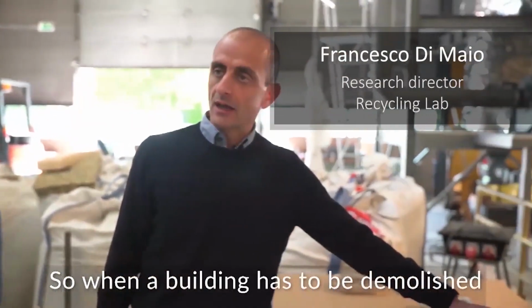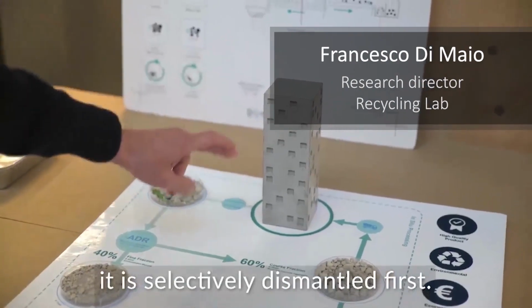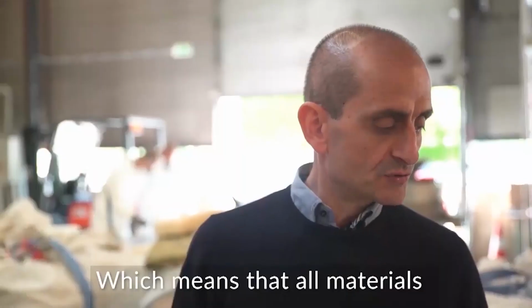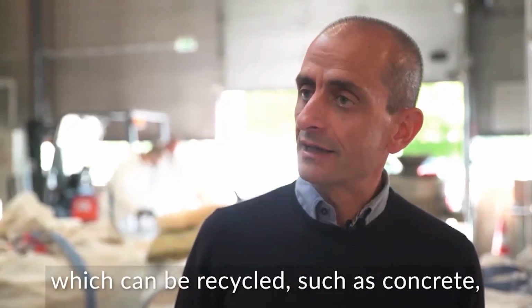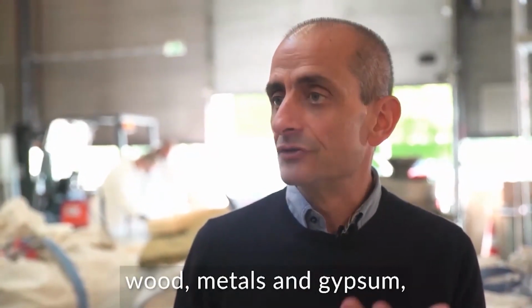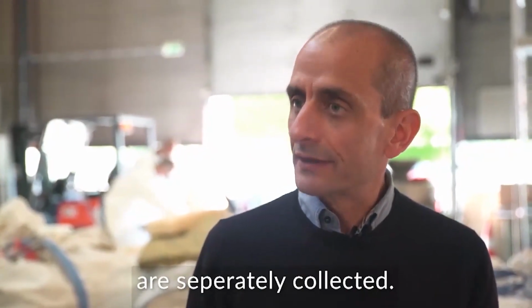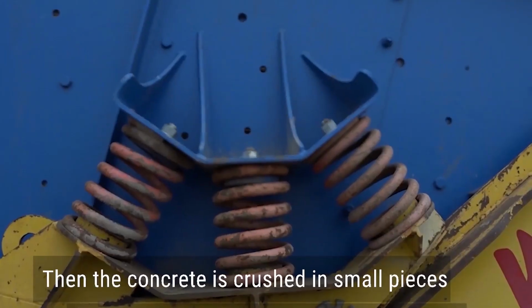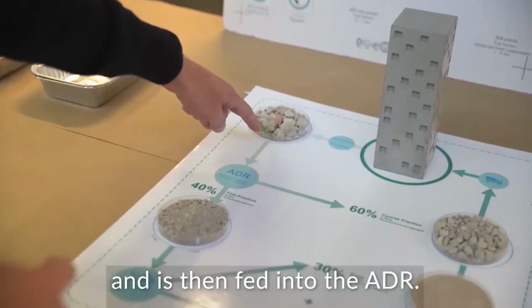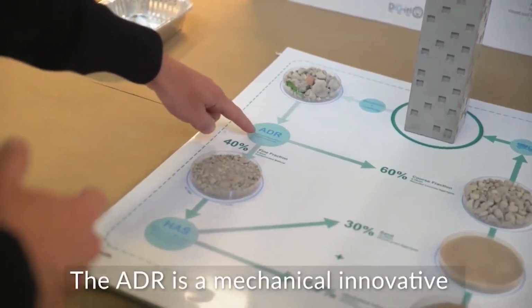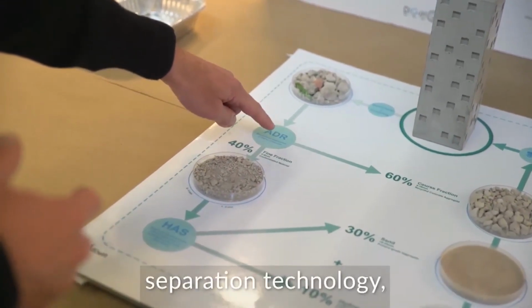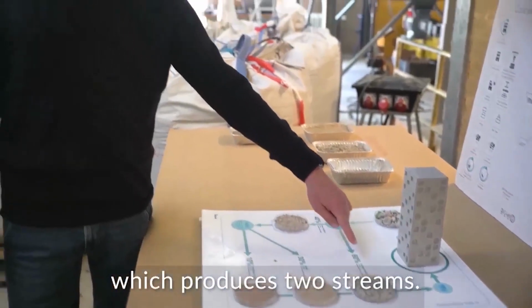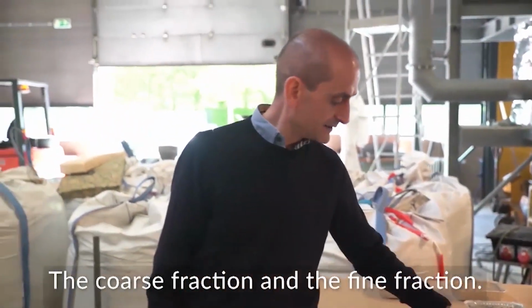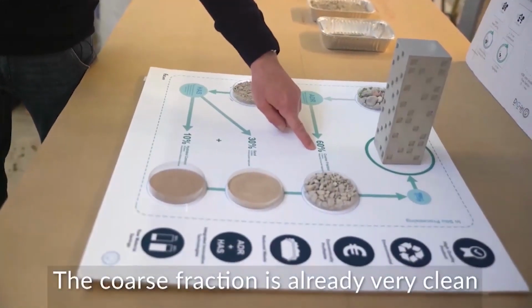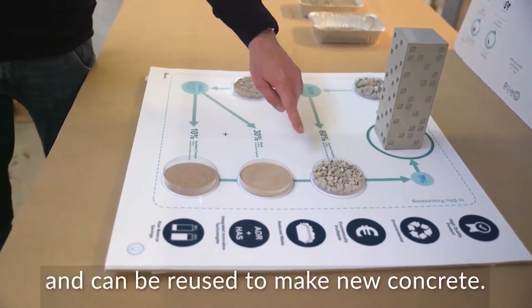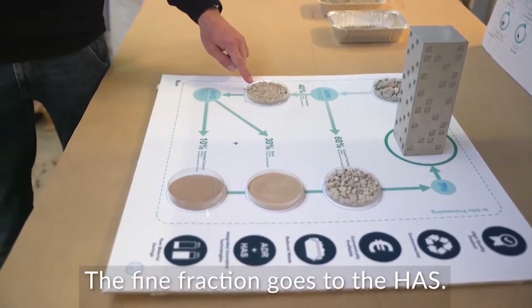So when a building has to be demolished, it is selectively dismantled first, which means that all materials which can be recycled, such as concrete, wood, metals, and gypsum, are separately collected. Then the concrete is crushed in small pieces, and it is then fed to the ADR. The ADR is a mechanical innovative separation technology which produces two streams, the coarse fraction and the fine fraction. The coarse fraction is already very clean and can be reused to make new concrete. The fine fraction goes to the HAS.